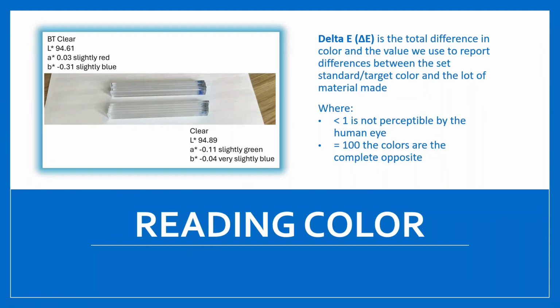In this case, as an example, you can see that there is some polycarbonate. One's a blue edge tint and one is a clear. And you see the blue edge tint has a slightly larger negative value for the B space, making it more blue than our clear does. And so that's where the blue edge tint comes from. It's more blue. It's further down on the negative B value for blue. So those are the coordinates for polycarbonate, blue edge tint, and water clear.